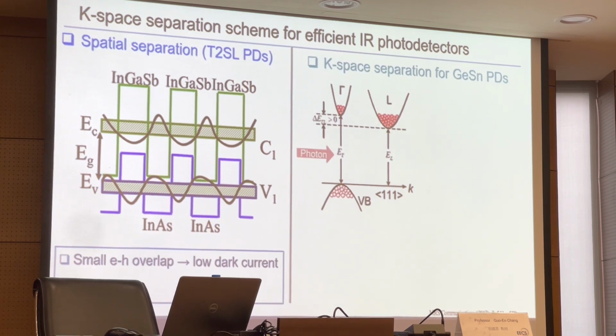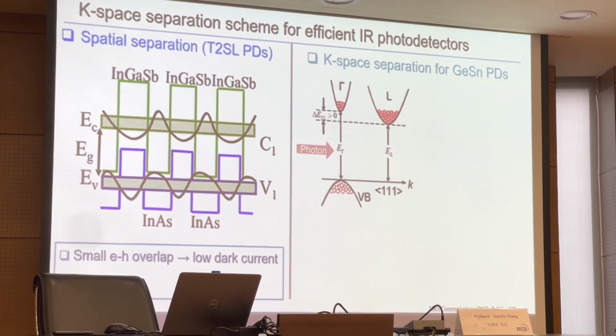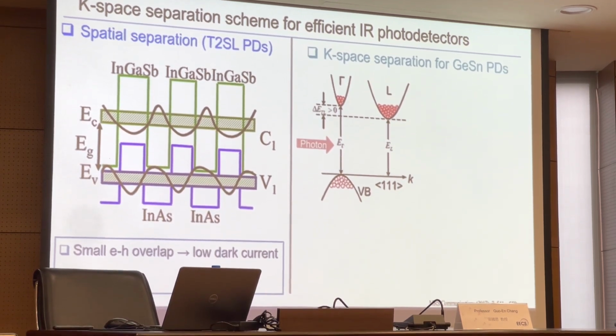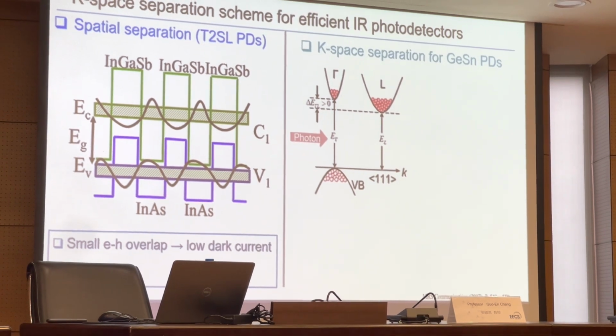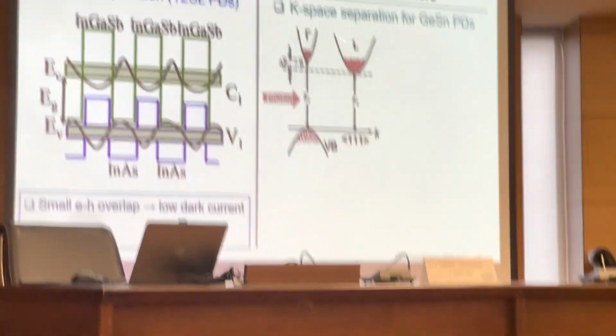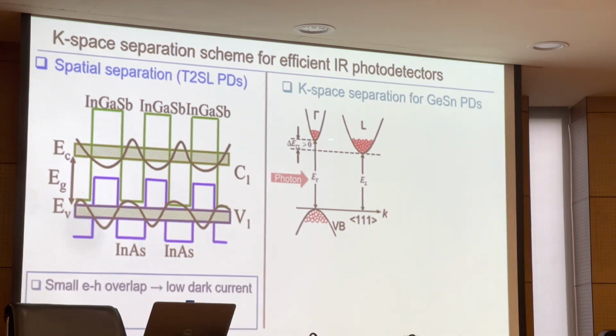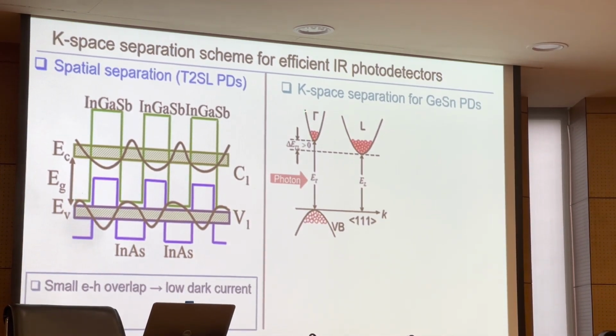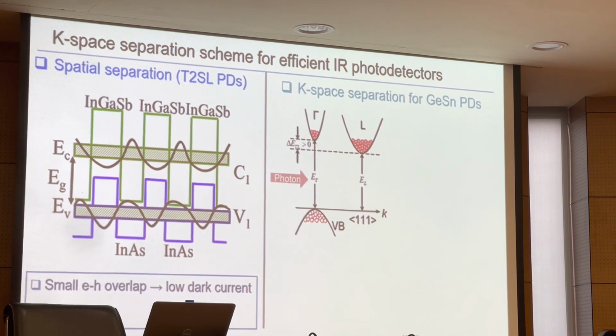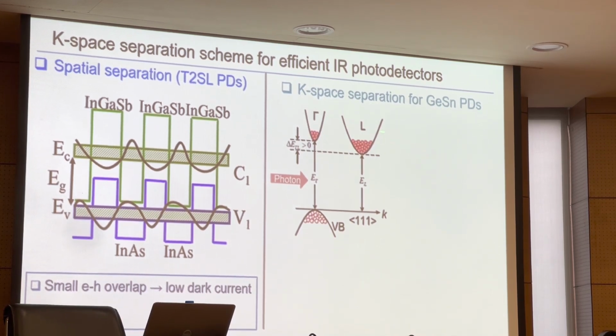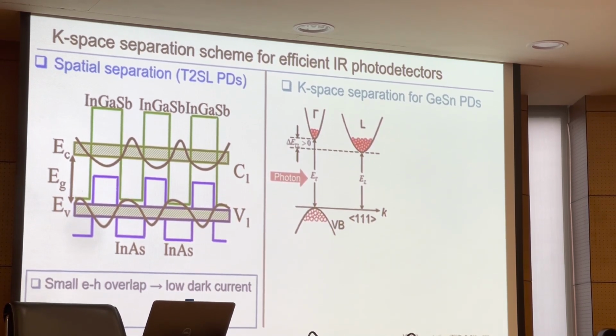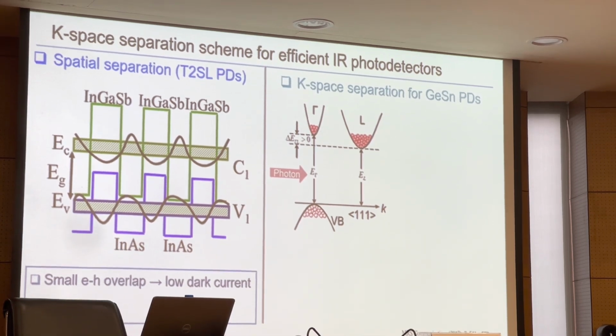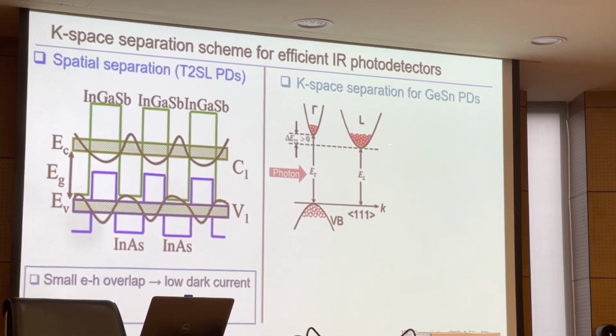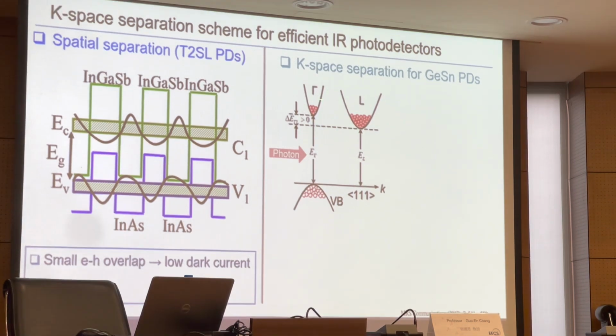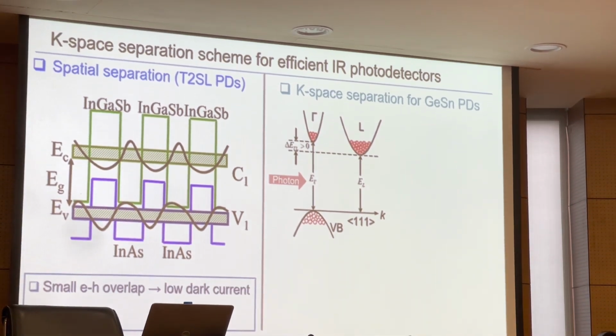For our germanium material system, it is a very unique system because in addition to the direct conduction band, we also have an indirect conduction band. The density of states of the L conduction band is very large, about 8 times larger than the direct conduction band.